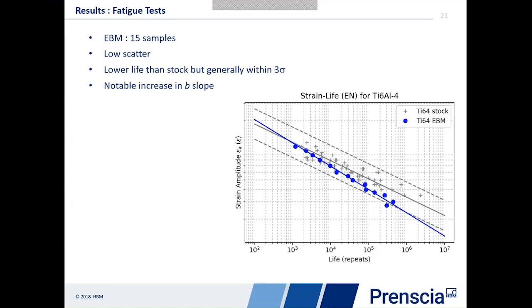If you find that there's lots of porosity in materials, it tends to have a lot of scatter away from that regression line. And the first thing we notice here is that's not happening. It's hugging the line quite nicely, and that means that we're getting good quality and consistency in what we're doing. You will notice that the lives are lower than the stock test that we're comparing them with, but they're not that much lower. They're within a sort of 3 sigma. The other thing that you notice is the slope, the B slope of the curve is slightly steeper. And again, this is what we'd expect.